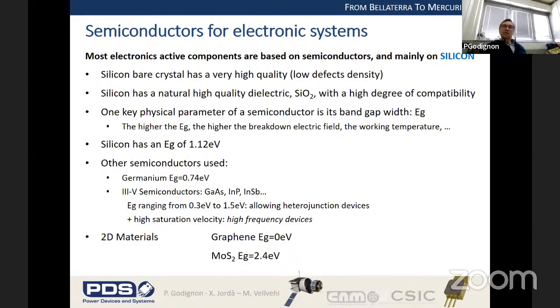So you have other semiconductors that you can find in applications, which are germanium, for instance, which has a lower gap, or III-V semiconductors like gallium arsenide, indium phosphide. With these materials, you can get a wide range of gaps between 0.3 and 1.5, which allows you to make so-called heterojunction devices, which are especially interesting for telecommunication components or very high frequency components.